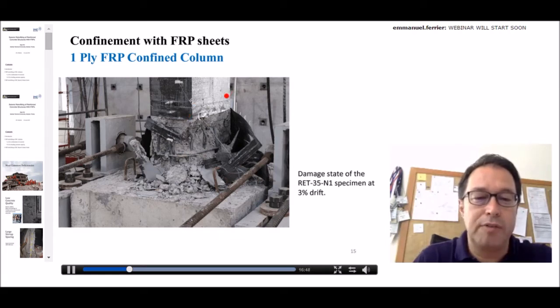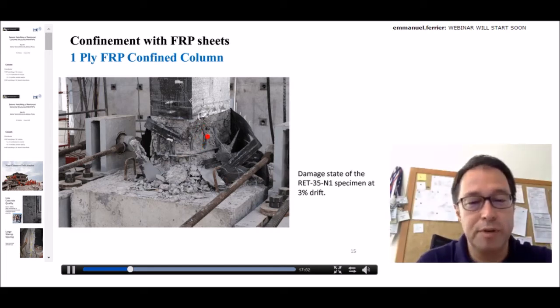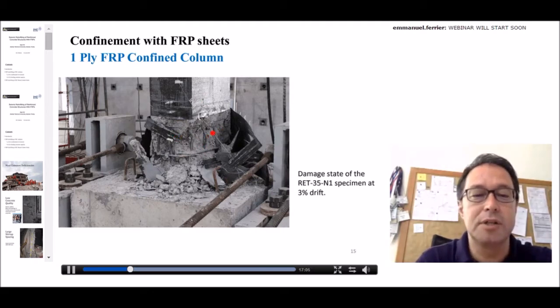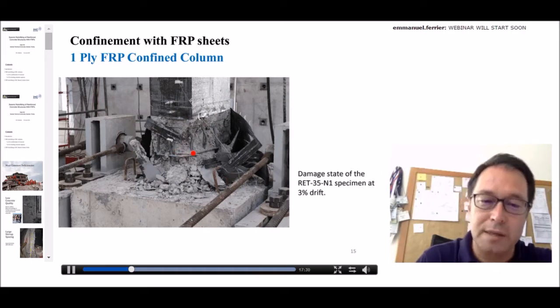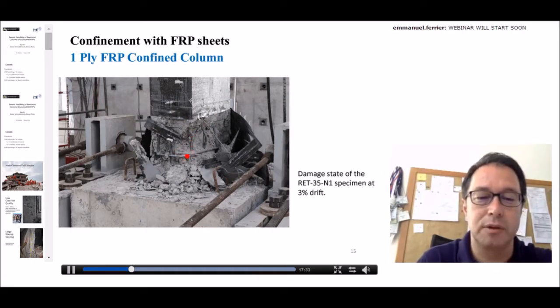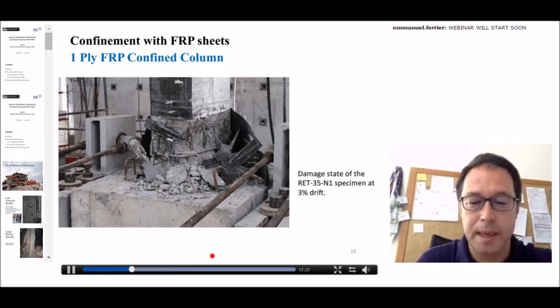We go to the specimen which is confined by one ply of FRPs, as you see here. This is the appearance of the retrofitted specimen at the drift ratio of 3%. As you see, again, we have some buckling of longitudinal bars in the compression zone. It may be interesting to see that since axial load is high, the compression zone is quite large. Therefore, we have buckling not only in the edge bars, but also in these bars, which are close to the middle of the section. Another important thing is that the stirrups were already open, with only 90-degree hooks. Whereas they provided some constraint against buckling of longitudinal bars, still, it's open at this point.